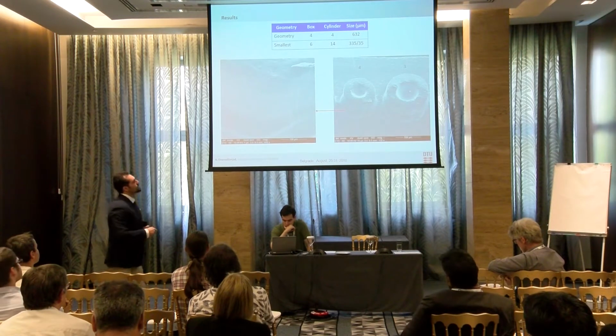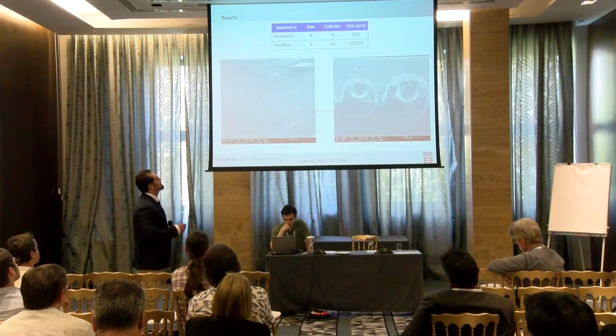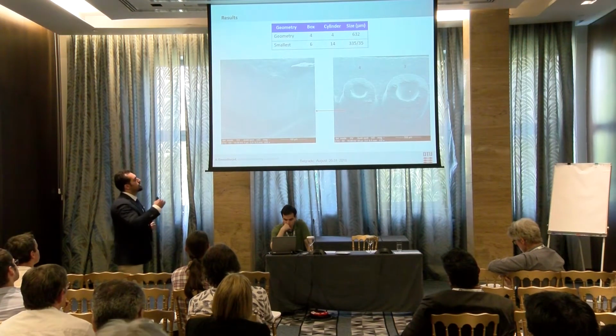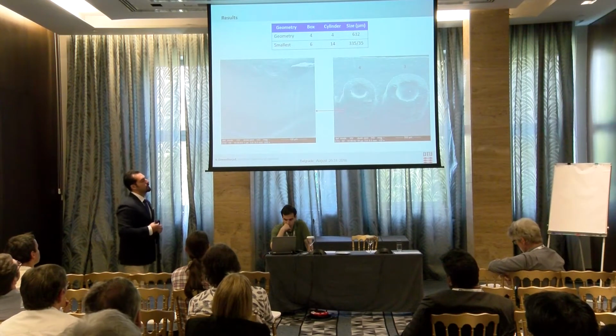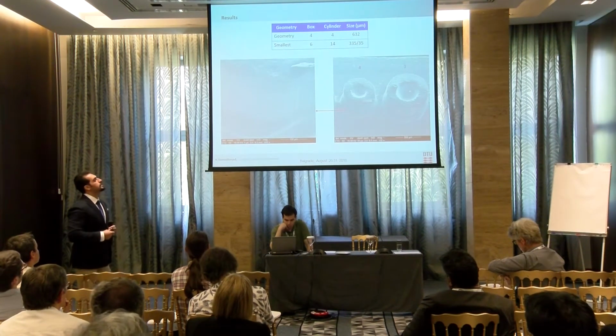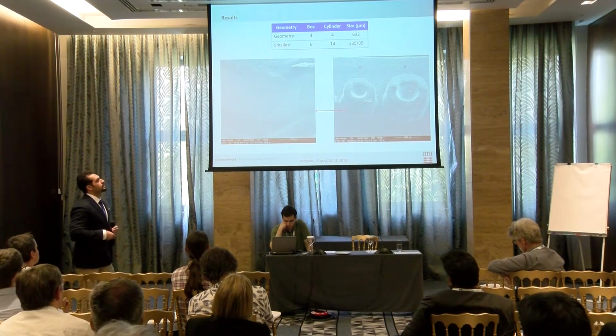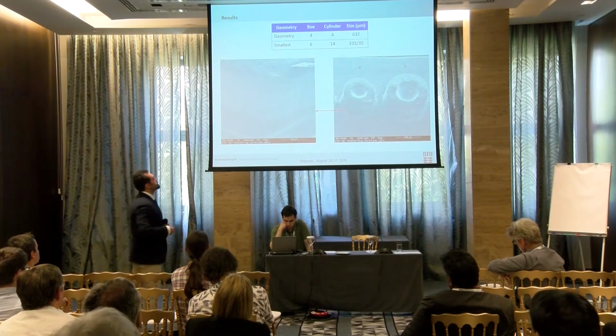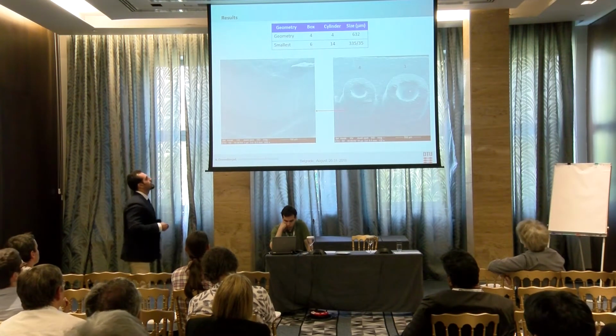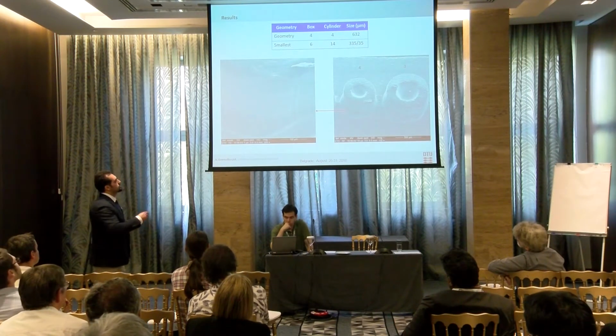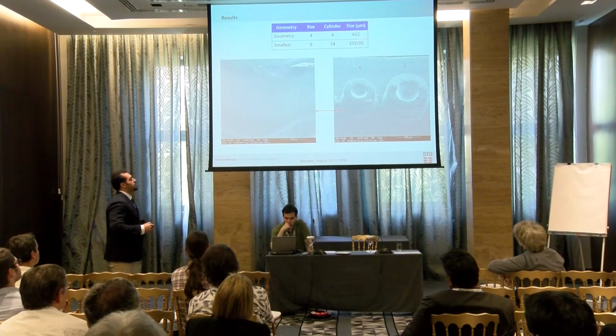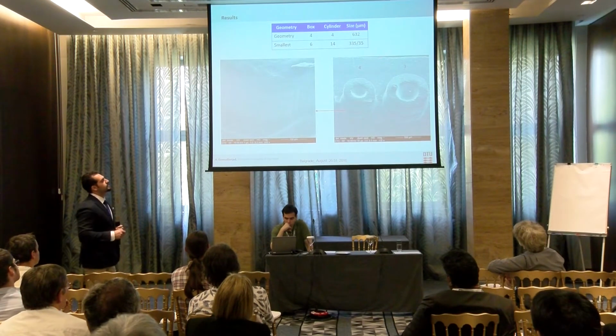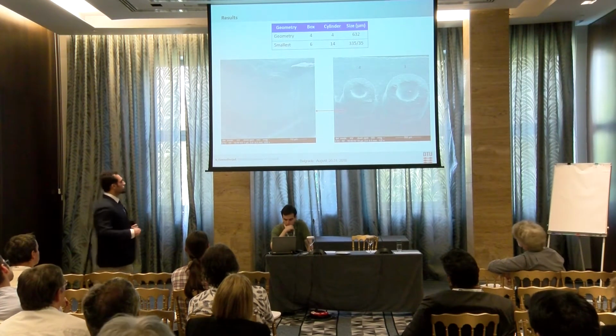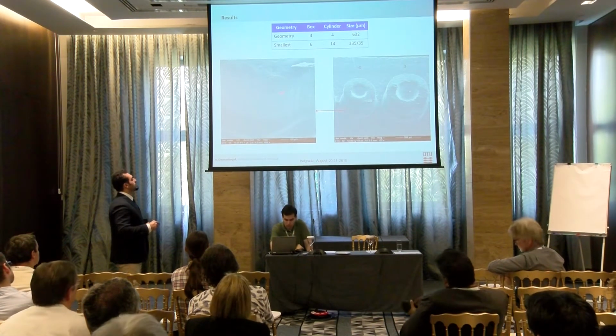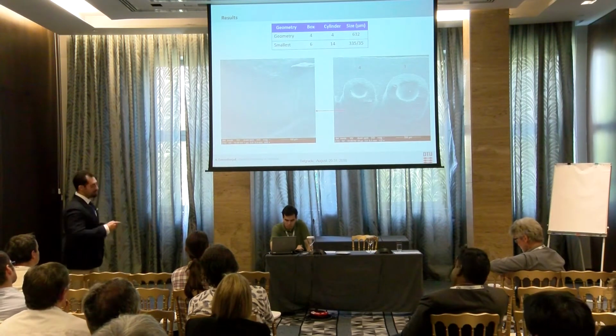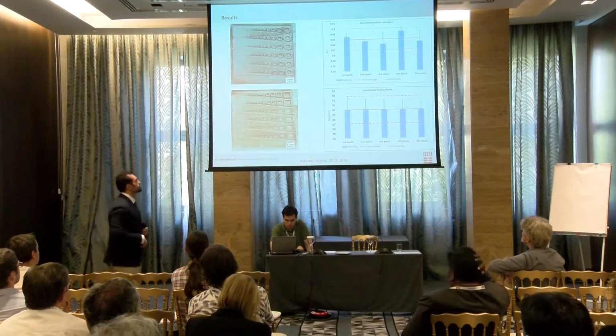In terms of the geometry, with the corrected geometry, the fourth column was printed for both boxes and cylinders, with a width and diameter of 632 micron, and the smallest print was column 6 and 14th, which was a geometry of 335 micron and 35 micron for the cylinder. And here we can also see the thickness of the layer with higher magnification, which was 25 micron.